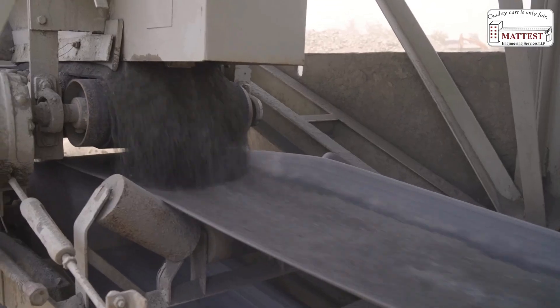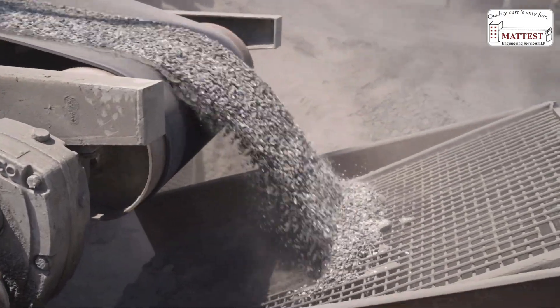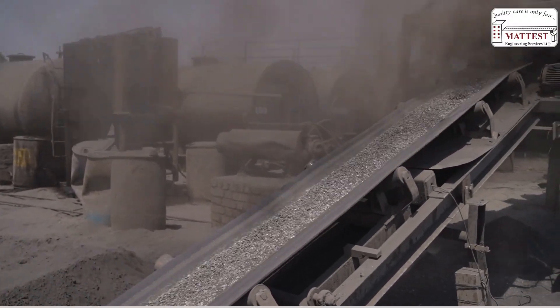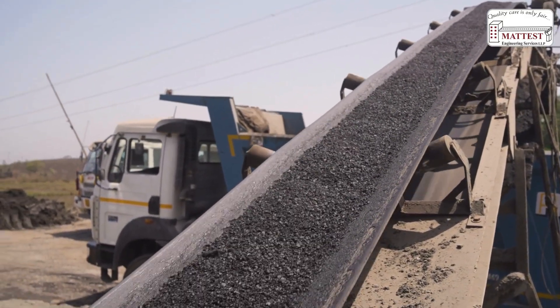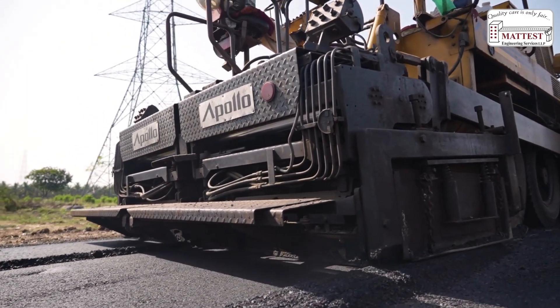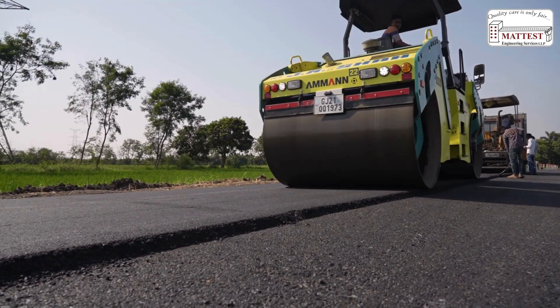In the manufacturing process, a hopper is added to the drum mix plant to feed waste plastic into the asphalt mix. The aggregate and plastic mixture is heated to 140°C–175°C in the central drum mixer to ensure uniform coating and melting. The plastic-modified bituminous mix is then loaded into transport trucks and delivered to the construction site. During laying, the temperature is carefully maintained between 110°C and 120°C, the paver spreads the mix evenly, and the rolling pattern and number of passes must follow construction guidelines.